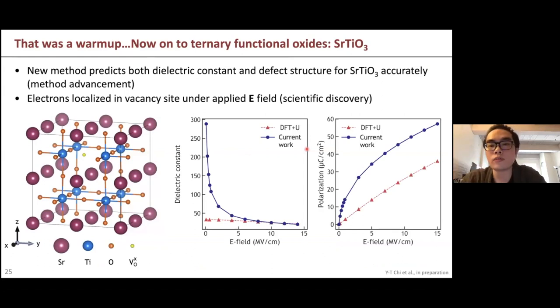Now we turn to the ternary functional oxide, strontium titanate. Studying the field effect in strontium titanate is not trivial work, because its band gap is not as high as the alkaline binary oxide. If you use the traditional method, you will either get a metallic solution, meaning the electron will not stay in the vacant site, or if you use DFT plus U, you will have a very bad dielectric constant, as I've shown here as a red triangle. It is orders of magnitude different from the real value.